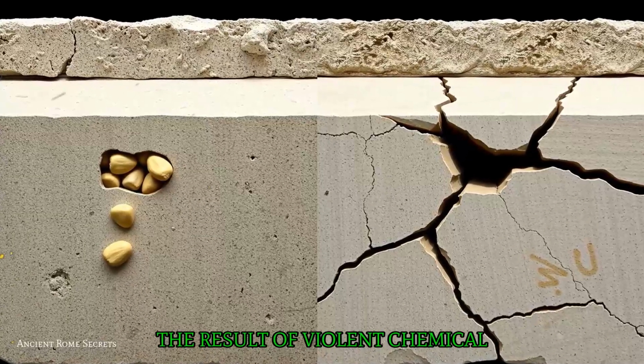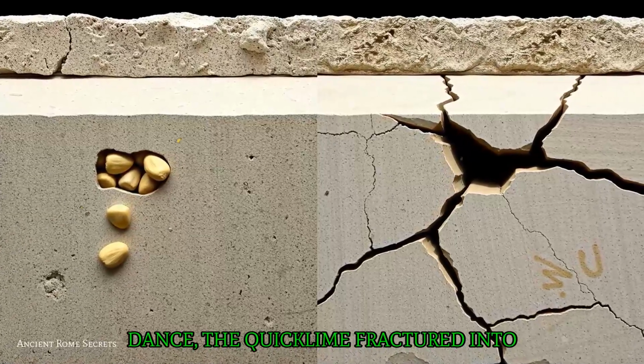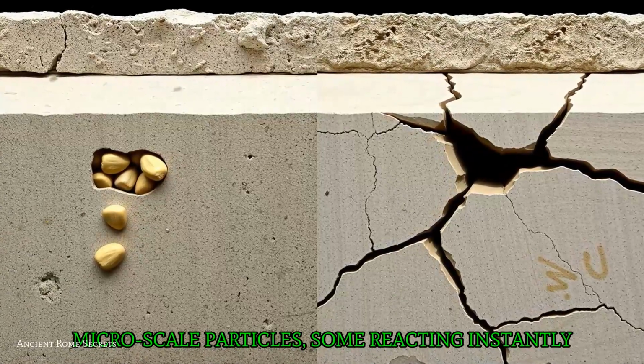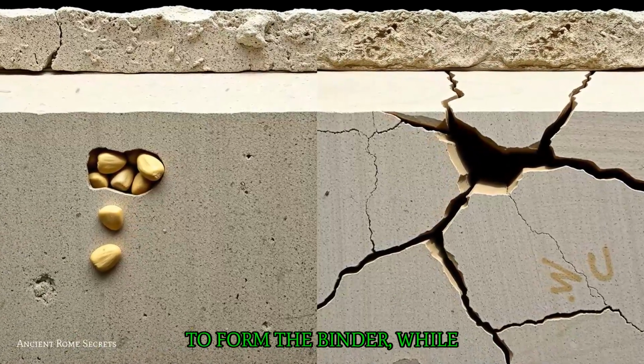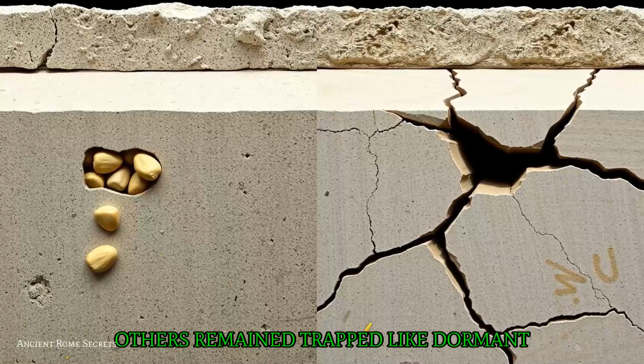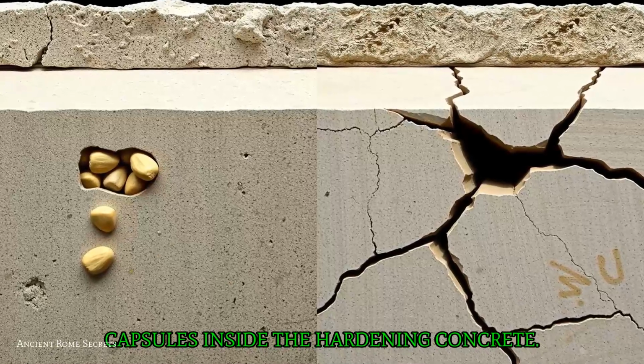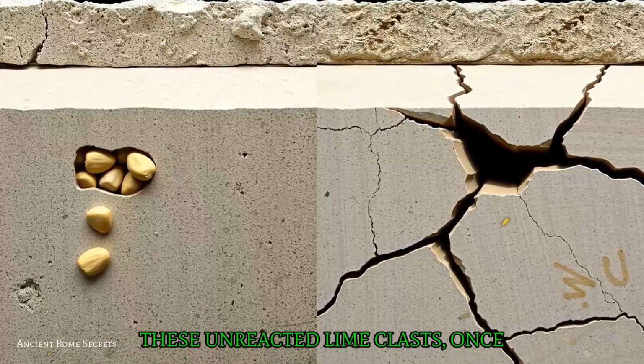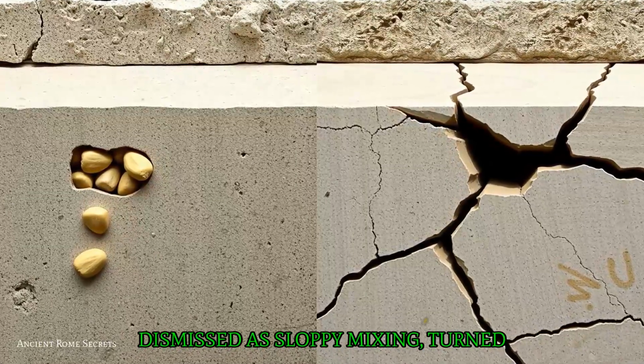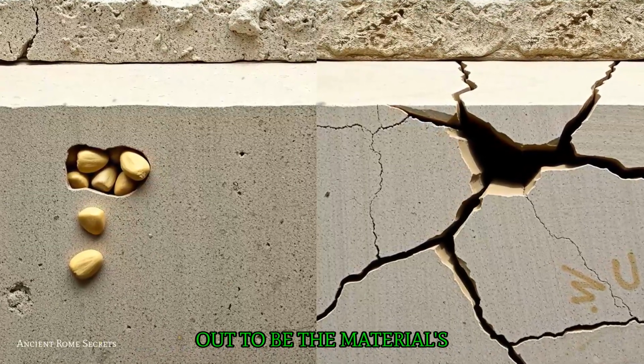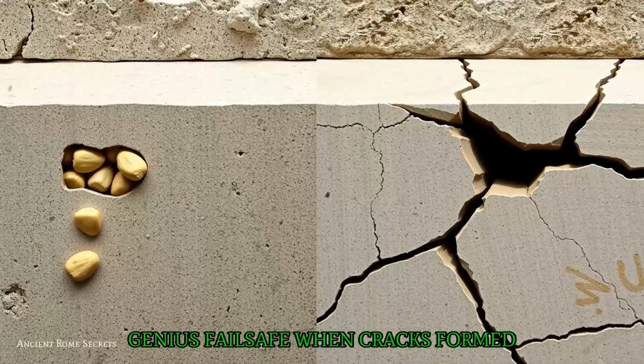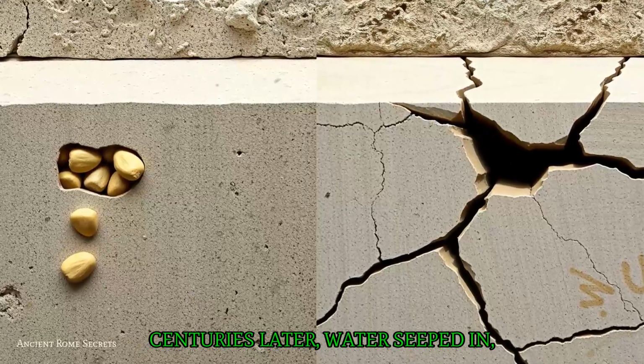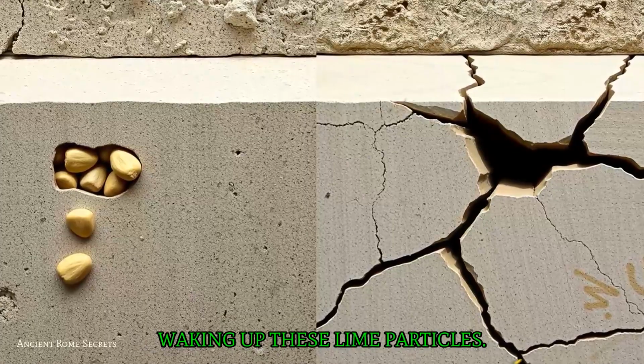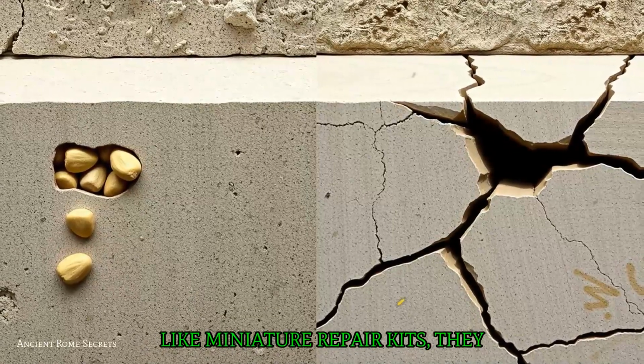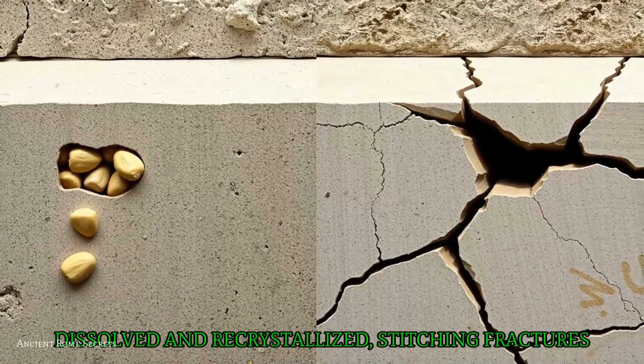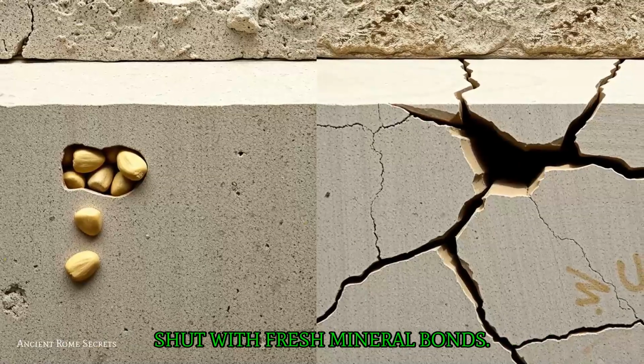The result, a violent chemical dance. The quicklime fractured into micro-scale particles, some reacting instantly to form the binder, while others remained trapped like dormant capsules inside the hardening concrete. These unreacted lime clasts, once dismissed as sloppy mixing, turned out to be the material's genius failsafe. When cracks formed centuries later, water seeped in, waking up these lime particles. Like miniature repair kits, they dissolved and recrystallized, stitching fractures shut with fresh mineral bonds.